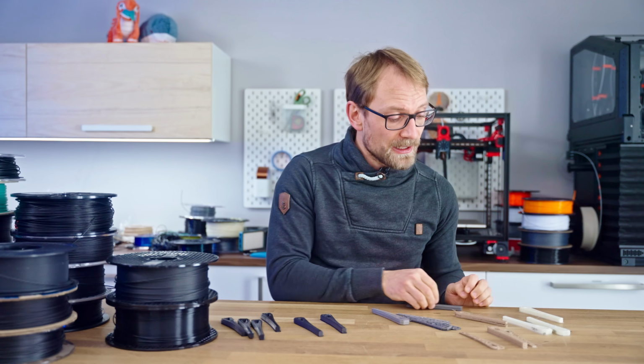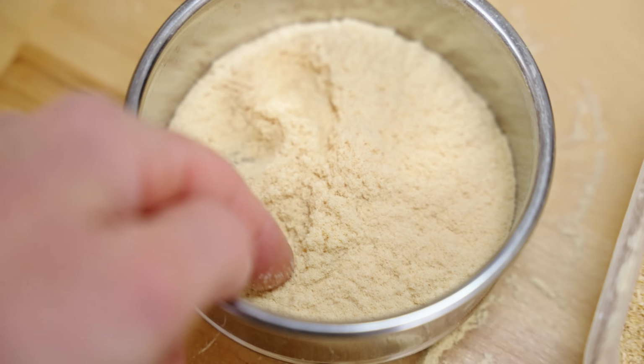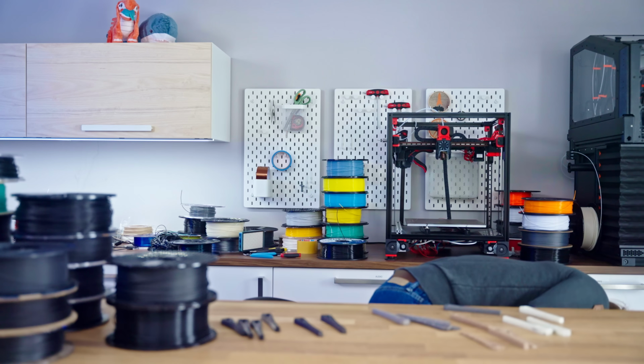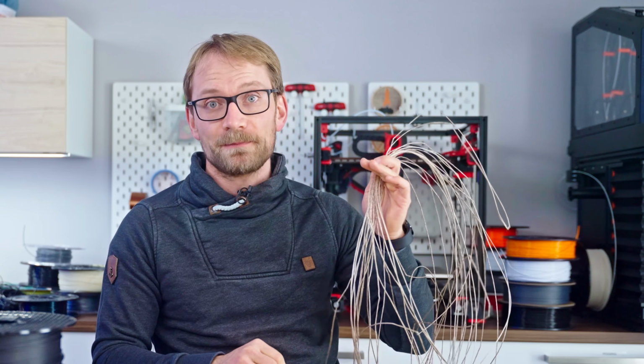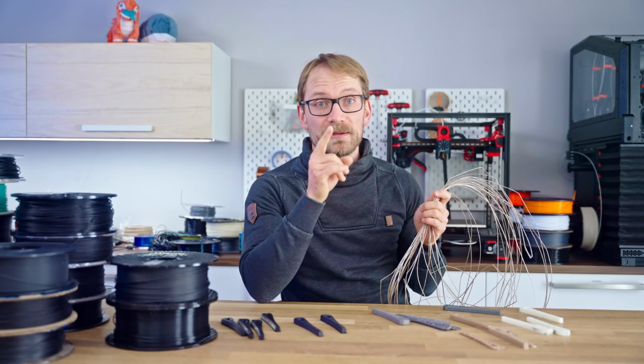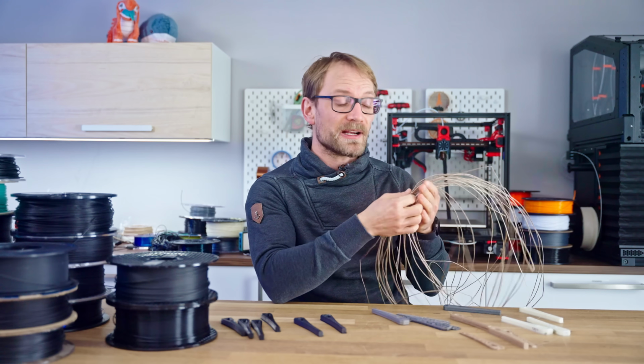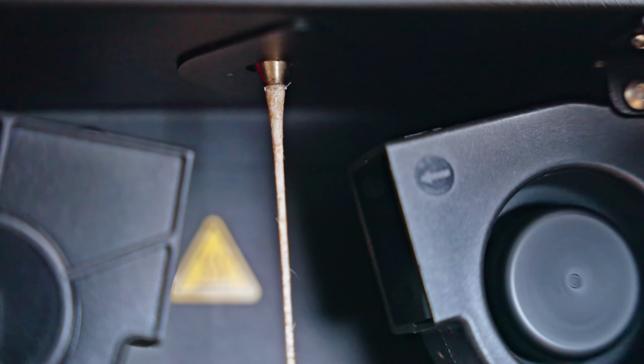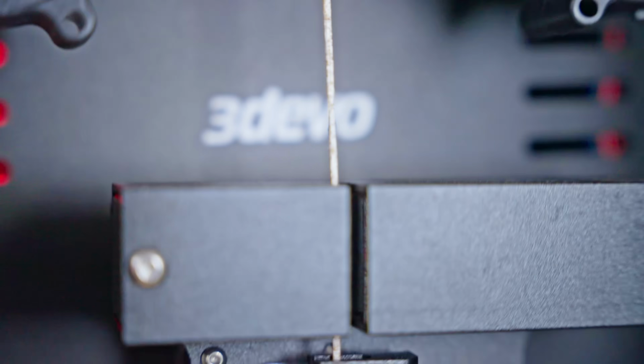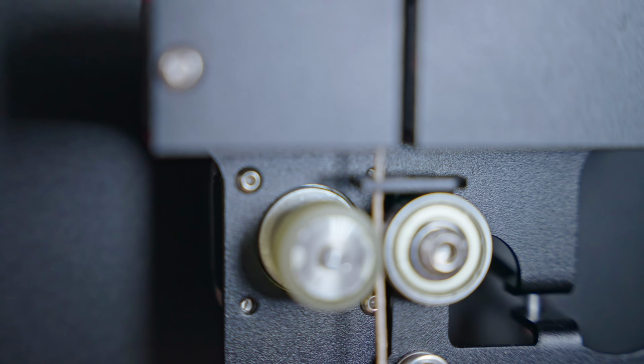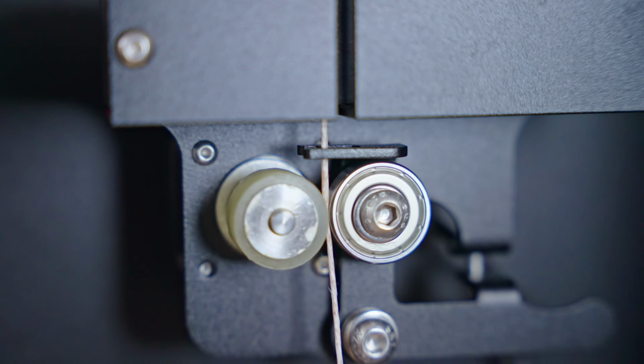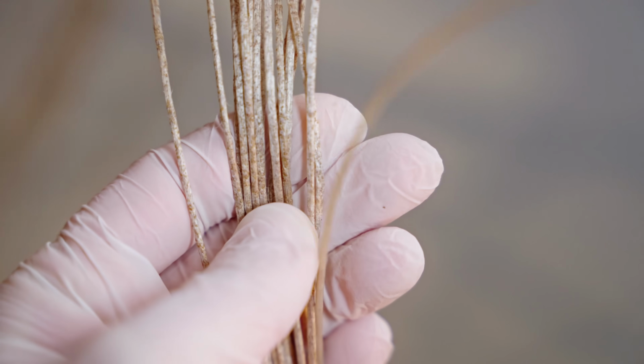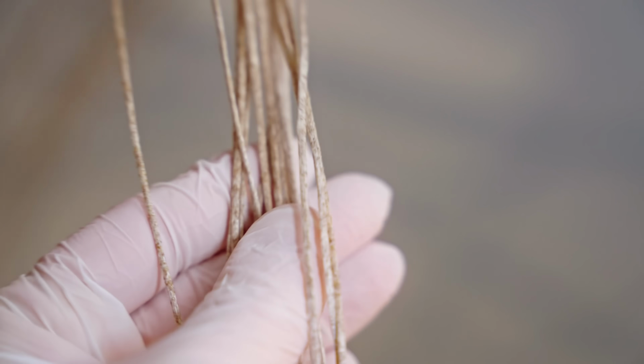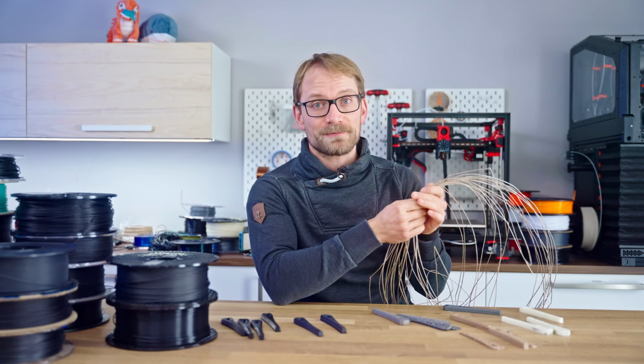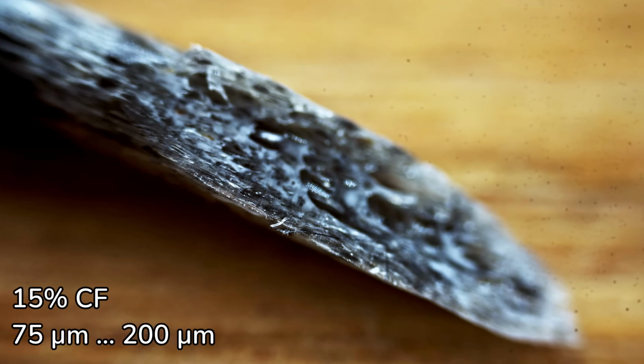If you're wondering why the part with the sieved wood fibers is missing, well, that's because, unfortunately, none of that filament was usable, and that's on me. I did fully dry the polymer, but not the chopped wood that I added in, so it ended up adding in too much moisture and steaming the filament into a foam. Because a foam is more squishy and harder to cool down, the puller wheels in the extruder ended up flattening the soft and still warm filament into a tapeworm shape, and that simply isn't going to work in any of my printers. But I think I was on the right track with my carbon fiber experience.